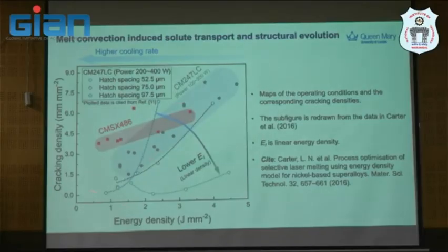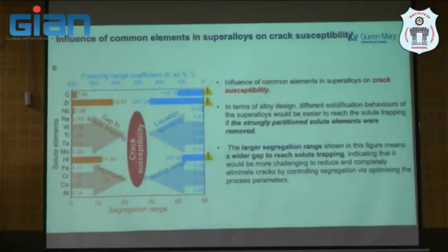You will see if you use lower density, your linear energy density is even higher, but your crack occurrence is actually lower. But in the case of CMSX486 here, it just shows a similar composition here. And this one contributes to the energy density that contributes to the interfacial velocity that we talked about previously. But that means this is a suggestion now: the influence of the common elements in superalloy on crack susceptibility. I mean, this can be found in the Nature Comm paper if you like, online. So the freezing length here will be varied as well based on the process parameter you use. Surprisingly, that means we cannot control it like casting. We know the freezing length is dynamic with the process.